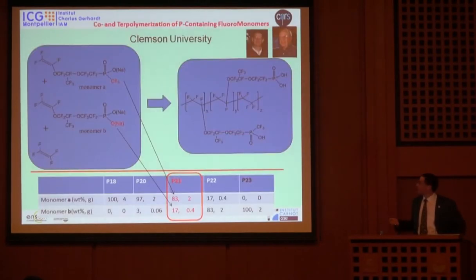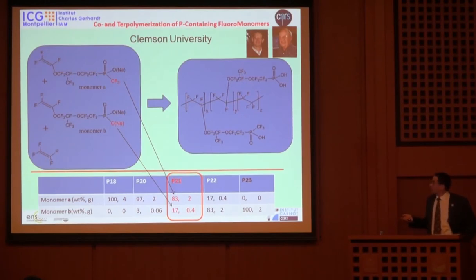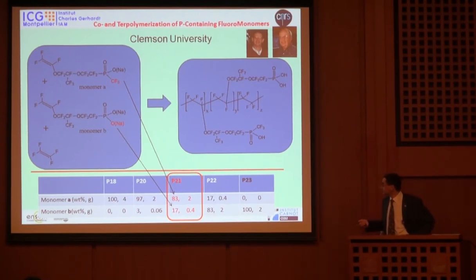And this same team, this is Daryl DeMarteau, and this is Steve Creager in Clemson, showed that they could also prepare some nice monomers, comonomers, perfluorinated ether containing a phosphonic group. Even they made a polymer with tetrafluoroethylene. And you can see the design and the composition is very important, because the phosphonic acid is going to bring the acidity, and you can work at higher temperature.